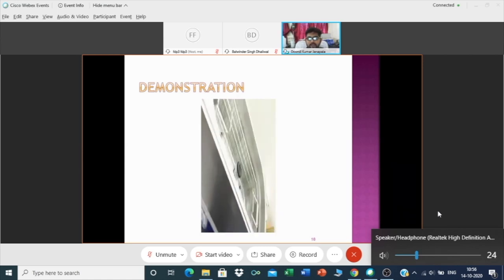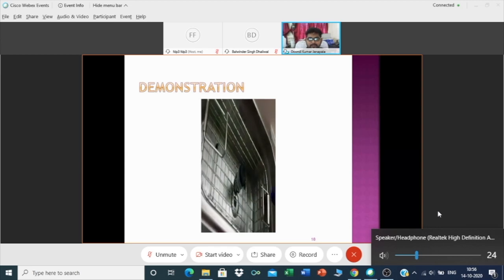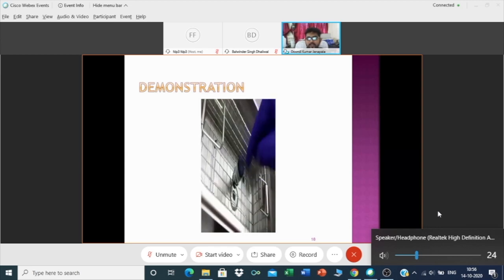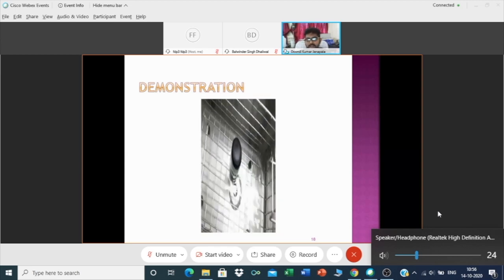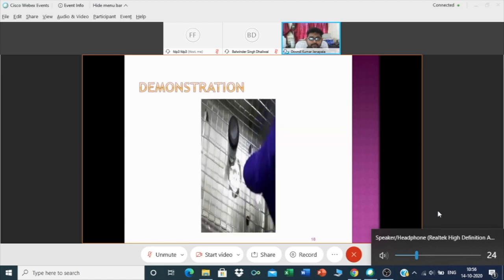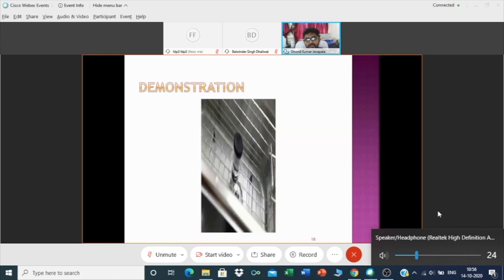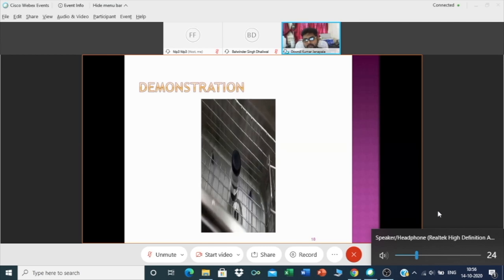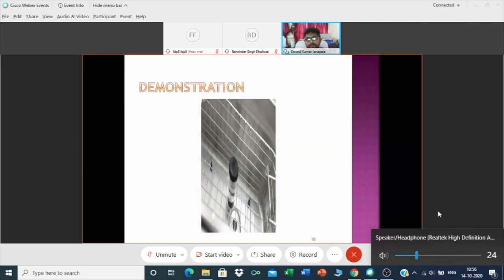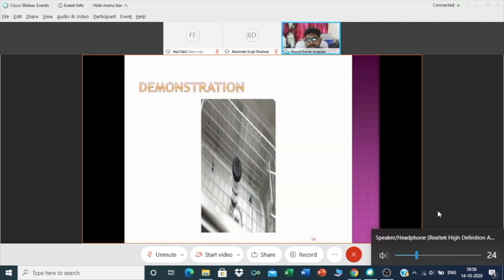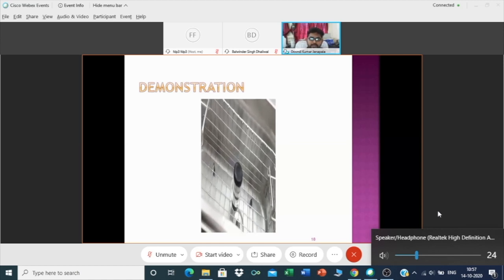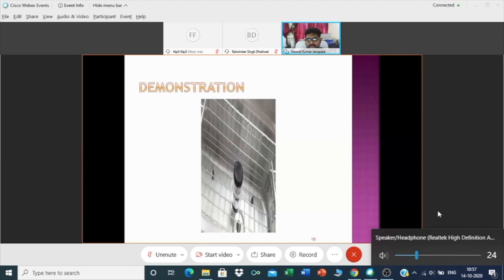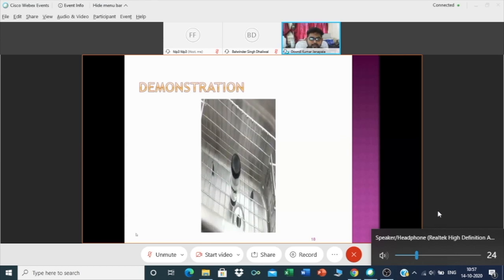So that is why you should consider reading papers on nanoparticle dispersion into various solvents. I will give you some references for that too. This particular equipment, the sonicator, costs, a basic one, some 20,000 or so. It vibrates at a very rapid speed, and your nanoparticles will disperse into the solution very uniformly. That is the reason we go for this sonication.